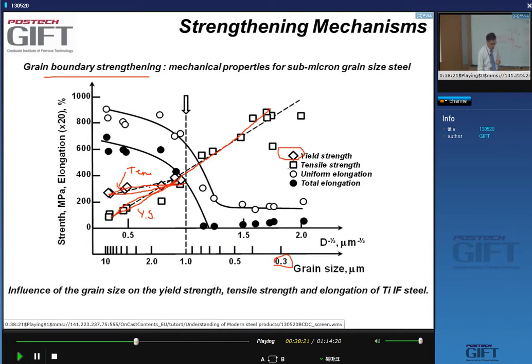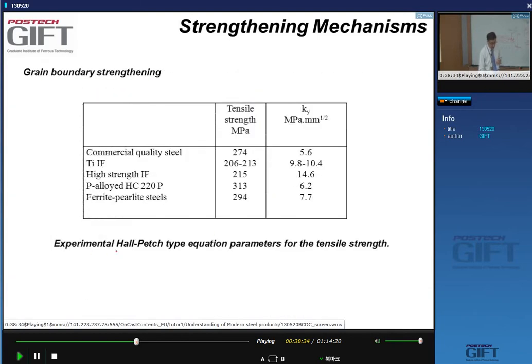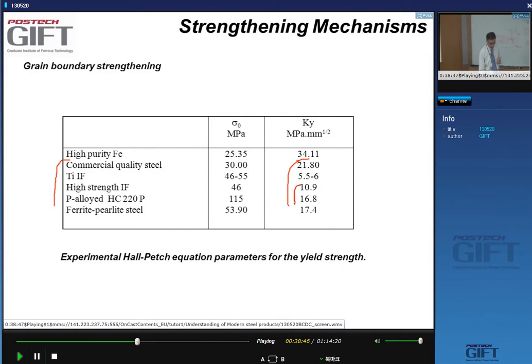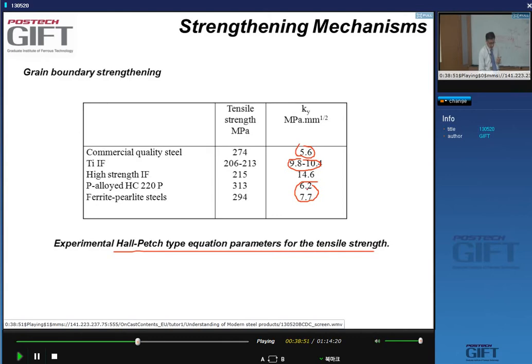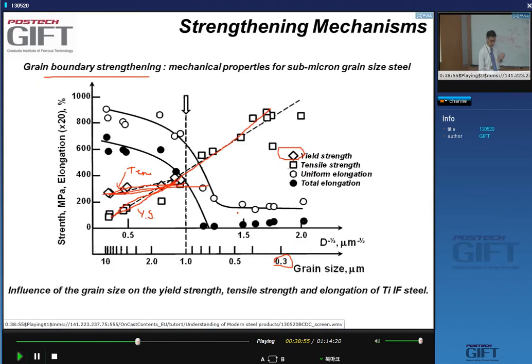However, the slope of the tensile strength, the Hall-Petch slope, is lower. If we go back a few slides, you can see a Hall-Petch type equation for tensile strength. In general, we see lower values. Here I have 10, and here the values are lower. So you get a lower slope. If I have a large grain size, the yield strength is here and the tensile strength is there, obviously. And if I reduce the grain size, the yield strength increases, the tensile strength increases also, but at a lower slope. So eventually they have to meet up.